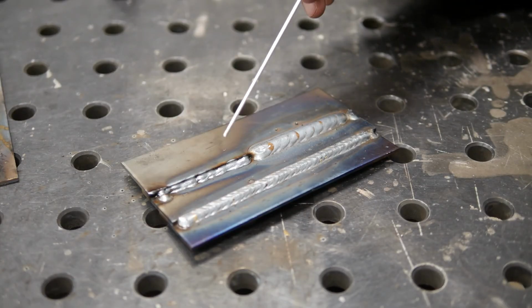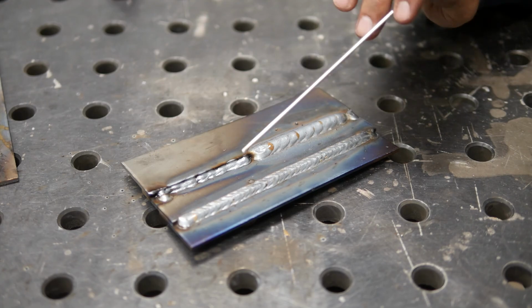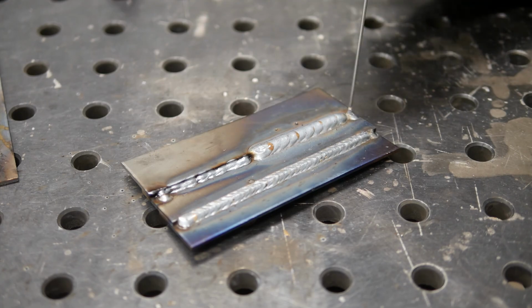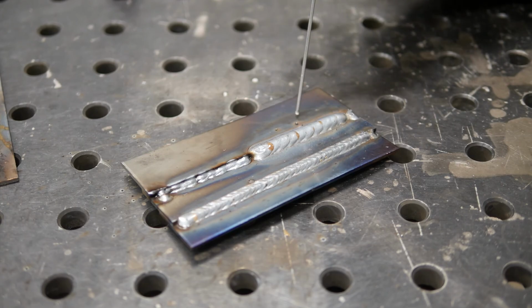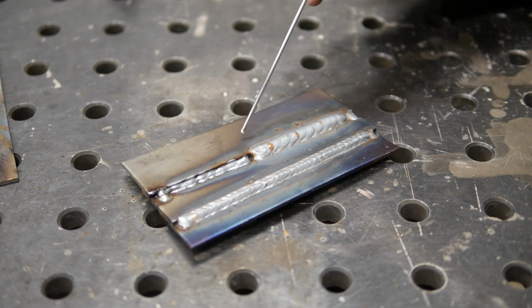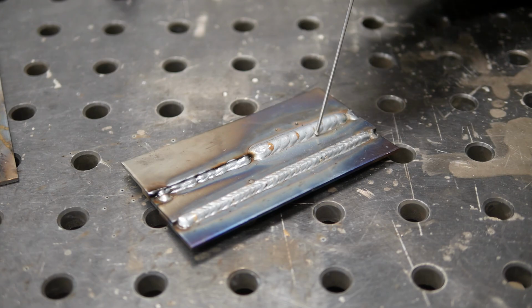Here's too slow, and here's too fast. And there's a problem with both of them. Let's look at too slow. This one I made big giant circles and hung out for a really long time. So I dumped too much heat into this plate and I've got this big heat affected zone. So I've got some unintentional warpage, and worse yet, I could have annealed the plate. That means outside of the weld in what's called the heat affected zone, I could have a weak spot. So the weld's not gonna fail, but the plate might prematurely fail.